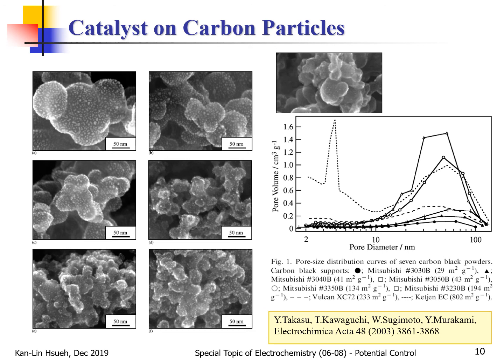If you use a conventional surface area detection technique like nitrogen adsorption, called the BET method, you are detecting the entire surface, because nitrogen adsorption cannot distinguish the catalyst from the carbon surface. It gives you the entire surface area. But for the fuel cell, only the platinum is really active surface area. So if you use cyclic voltammetry, you measure the active area of the platinum rather than the carbon area, because hydrogen adsorption only takes place at the platinum area. In the carbon area, nothing happens, only the double layer charging current. In this way, you can distinguish the real available platinum area in the catalyst region.